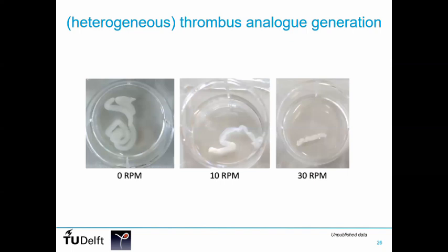They can be pretty long, and this one here, especially in the central part, you can also see that there's some heterogeneity in there, and these of course are platelet-rich, platelet-poor, I'm not sure. At least there are no red blood cells in here, but you can see that there is some heterogeneity in these thrombi. There are differences between the heads and tails and the central section, and this seems to be a very cool process, although it's pretty hard to control. So even if you're very careful, you can get different thrombi with different compositions under identical conditions, using identical protocols.